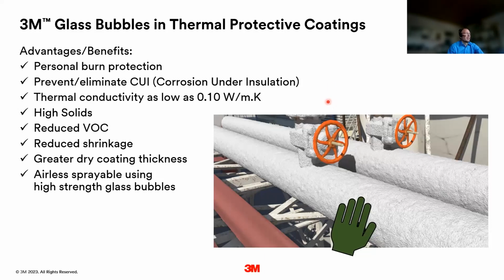Here our coatings that are highly filled with bubbles with a high solid content, and which are applied in a few millimeters thickness, can be interesting to decrease the surface temperature below typically 60 degrees C. Therefore, you don't need housing or additional insulation anymore.